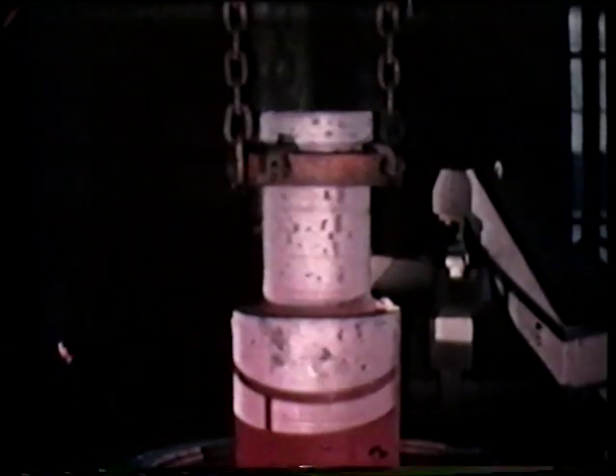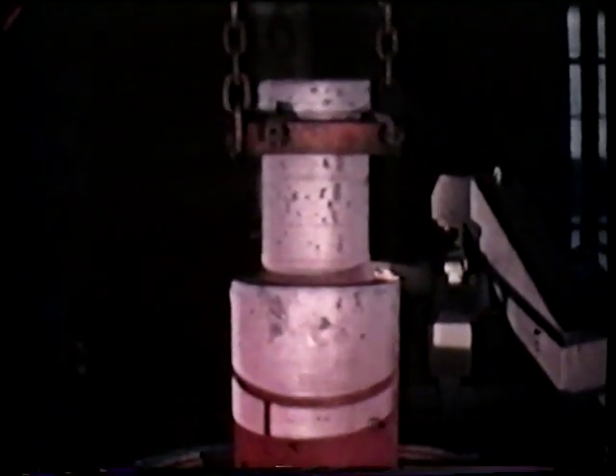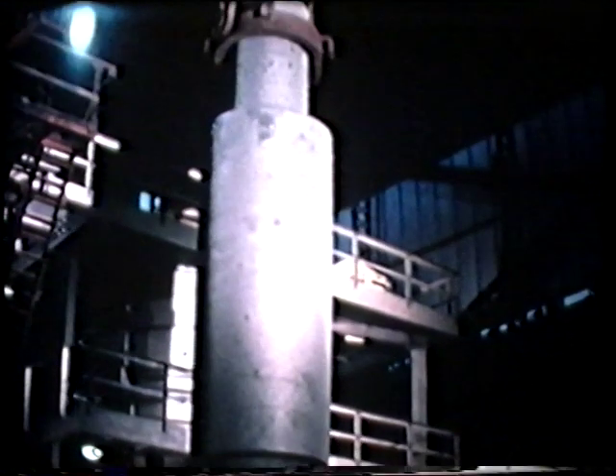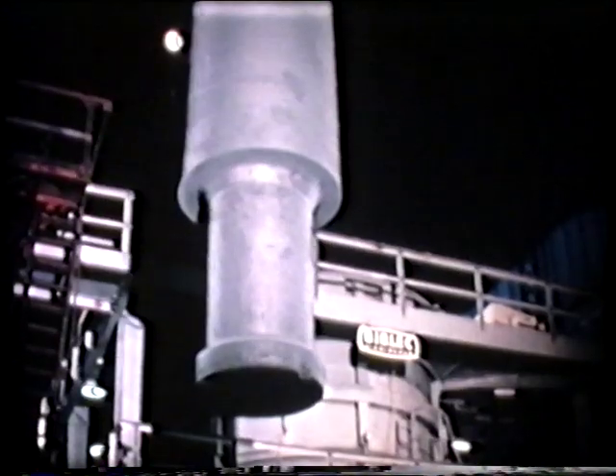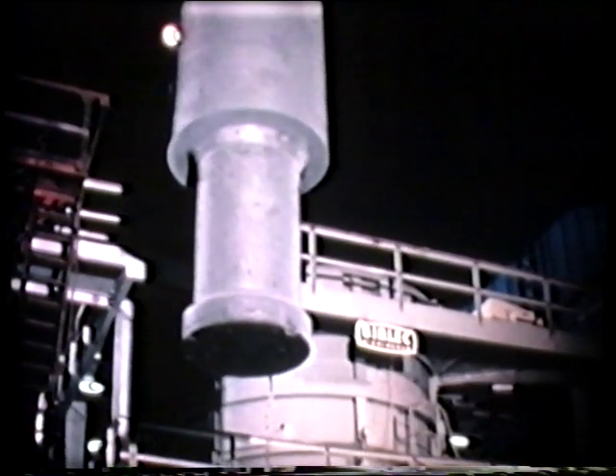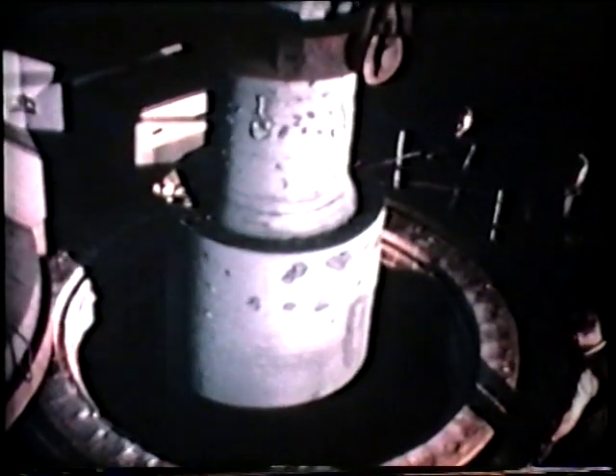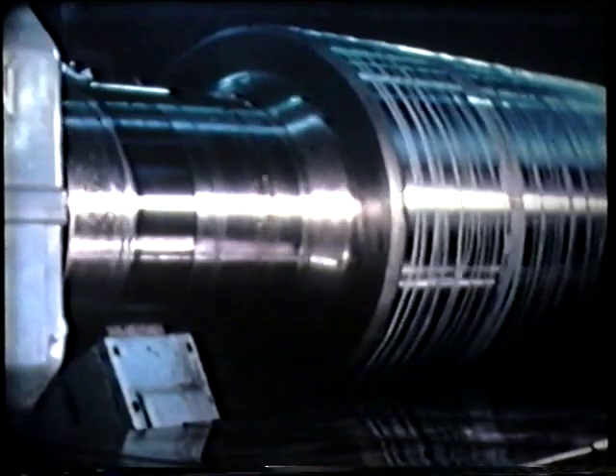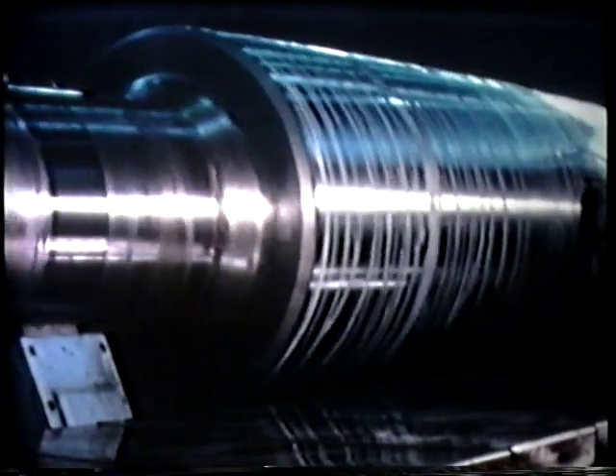A second heating cycle further modifies the structure of the steel, after which the roll is withdrawn for cooling in air. When the barrel has cooled to the specified temperature, the casting is returned to the furnace for tempering. This treatment produces the required hardness and also improves the ductility and toughness of the material. The final operation is grinding to a high degree of precision.